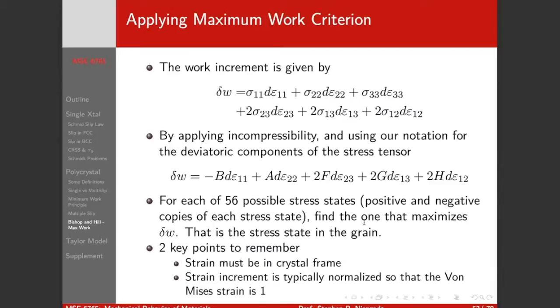We have to consider both positive and negative copies of the stress states, because the stress could be either tensile or compressive. We're going to find the one that maximizes the work done, and that's the stress state in our grain. So Bishop and Hill did a whole lot of theory to arrive at a really simple numerical approach to determine, from the deformation gradient, what the stress is going to be.